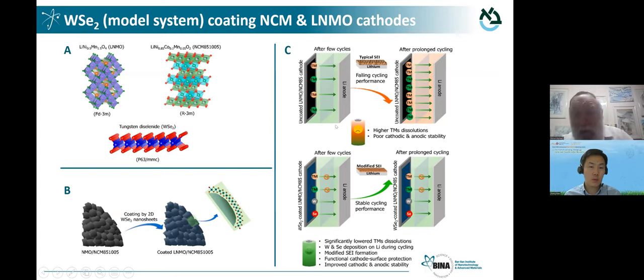And also, we have an effect on the negative electrodes. While we start with coating the cathodes, we have migration of the material to the negative electrode, and we have mitigation of the reactivity of lithium anodes as well. And the results are impressive.